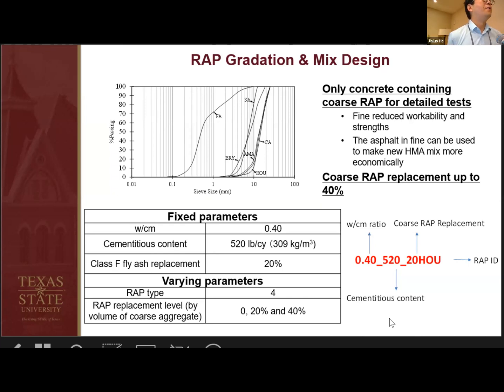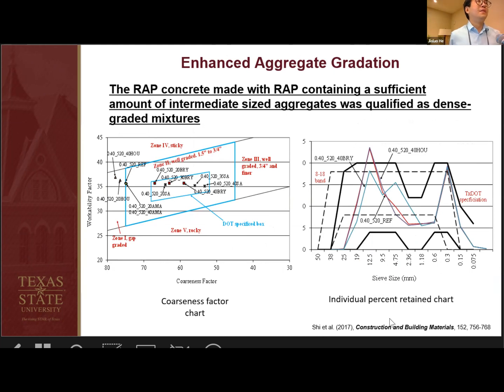We used a typical Texas DOT Class P paving material mix design, and we just modified the mix design by introducing RAP. The other objective of the project was to use RAP as an intermediate aggregate source to optimize aggregate gradation in RAP concrete. The reason is that the asphalt industry uses a smaller aggregate size, so RAP aggregates are smaller compared to the virgin coarse aggregate we use in concrete. So we were able to design dense graded RAP concrete by using RAP, which has more intermediate particle sizes.